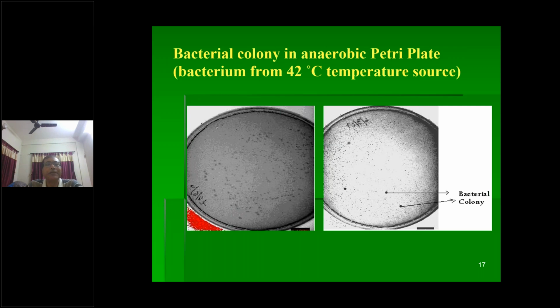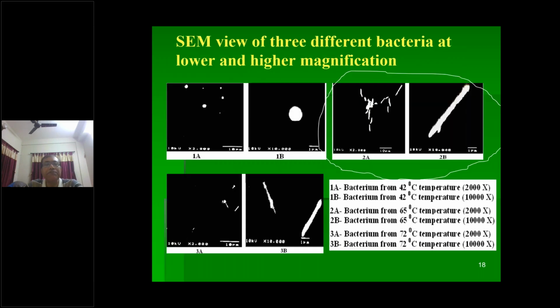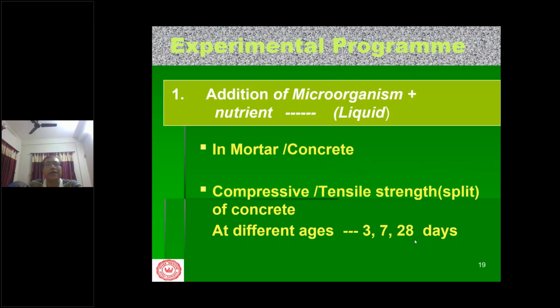From the 42-degree temperature, you have seen the SEM view of 3 different bacteria. 1A and 1B is for 42 degrees C, almost round shaped. 2A and 2B is actually a fiber shape. 3A and 3B is for 72 degrees C. It is also like a fiber shape.